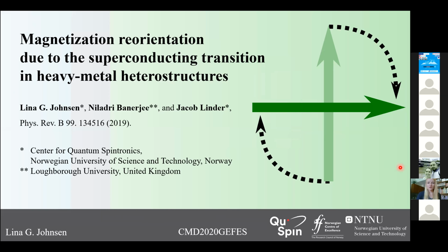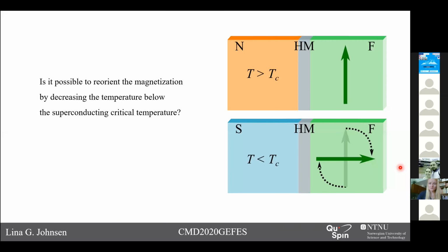Okay, I'm going to talk about reorientation of the magnetization in superconductor ferromagnet structures. And we'll look at the system with a superconductor, conventional superconductor, and a homogeneous ferromagnet, where we have a normal heavy metal at the interface that boosts the Rashba spin-orbit coupling.